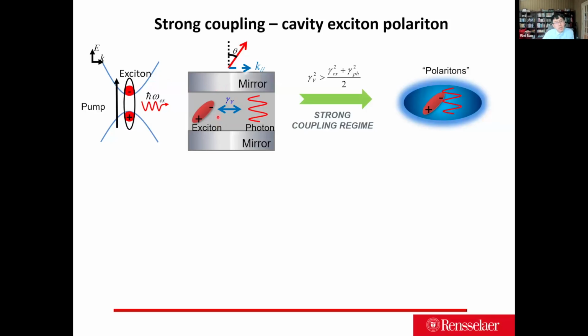So if you embed this exciton semiconductor into the cavity, and you make the cavity very good, and the semiconductor also, the majority of the emission during the exciton recombination goes into the photon. So what will happen is your exciton will emit a photon, and the photon is trapped in the cavity and reabsorbed by the semiconductor, regenerating the exciton. And this happens back and forth at a rate much larger than the exciton non-radiative decay rate, which is where the exciton decays without giving a photon, plus the photon decay rate out of the cavity. Essentially, once the photon escapes from the cavity, you are going to see a photon loss.